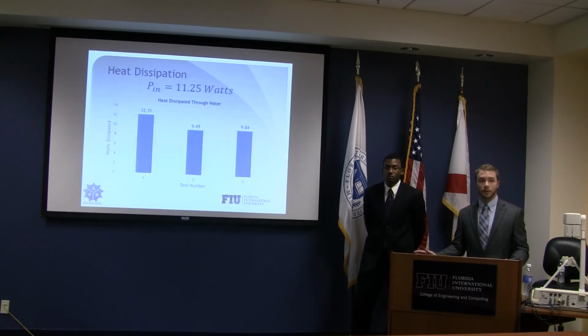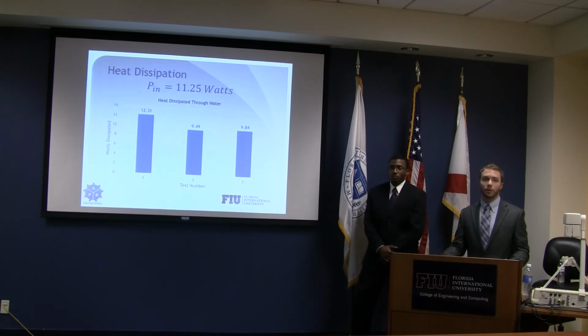So these are the tests that we did. We had a power input from our generator that was 11.25 watts, and as you can see, the 3 tests came very close to that. The first one is somewhat of an anomaly because it has higher convecting power than was actually being put into the system. The second 2 were what was to be expected, especially considering that you will lose some of the heat through convection of the actual board itself and not through convection through the water.